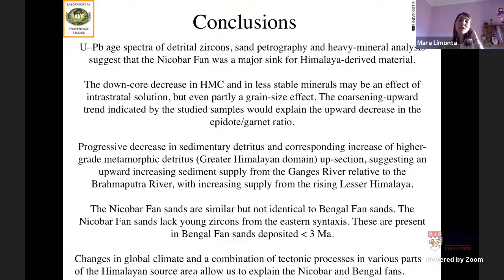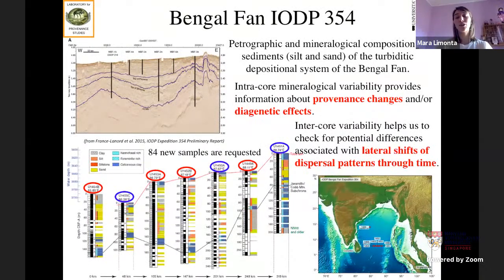Now I can show you a little bit the idea of the work on the Bengal Fan. I received 2 weeks ago the new 84 new samples to analyze. We want to do petrographic and heavy mineral composition of silt and sands, also of turbiditic sediment. We requested about 7 samples from the shallow core that are here in red, and about 15 to 20 in the deeper core that are in blue.